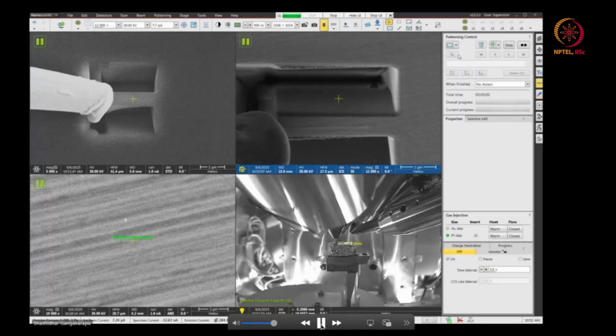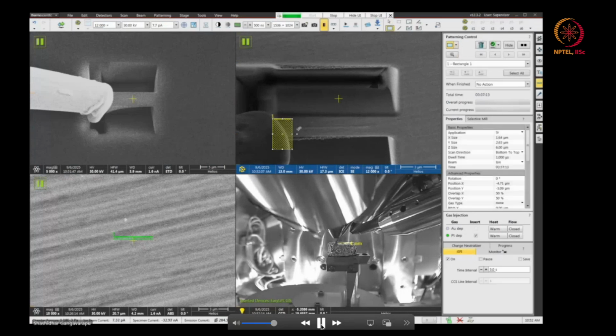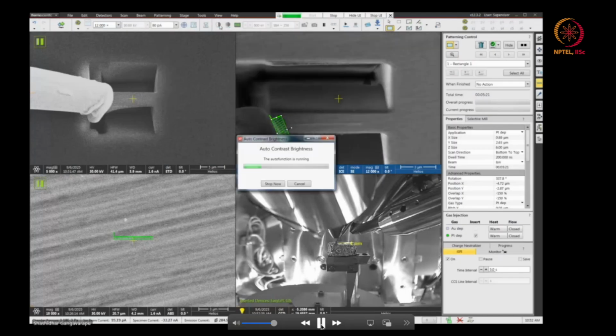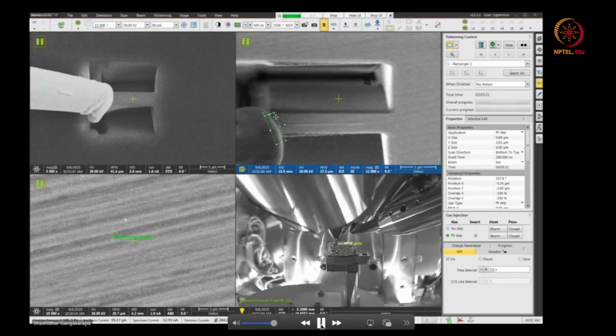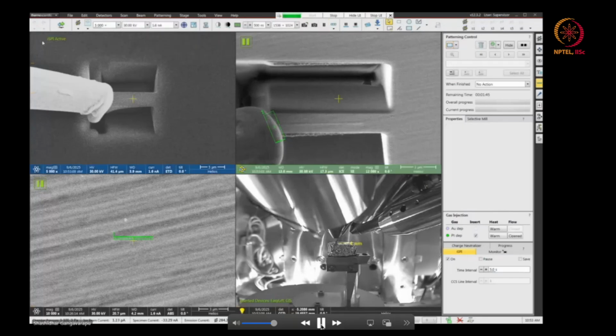Yeah, now I change the current value. Yeah, sorry. First, I'll draw some pattern. Same rectangle pattern. Now we'll make a bond of platinum with our sample, and now I change the current from 7 picoamperes to 80 picoamperes. So basically at 7 picoamperes, it's very difficult. It will take a long time to weld. So that's why we increase the current a little bit. Now the Z we put around 2 micron and XY is basically 0.8 and 2.